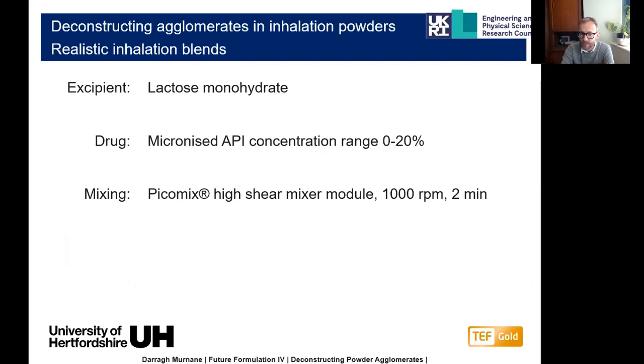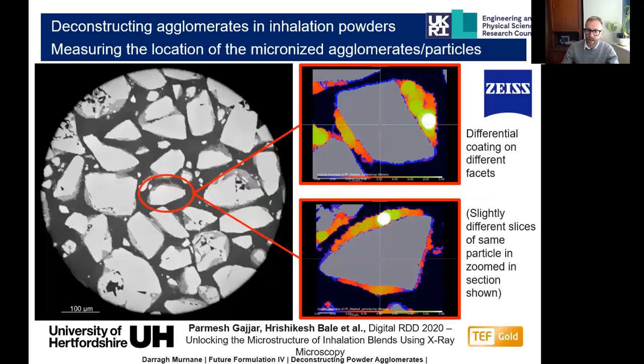We used the PicoMix, which is a small scale simulant of an industrial scale high shear mixer. Subjected it to 1,000 RPM mixing high shear for 2 minutes, which we've taken as a standard from previous literature studies using the PicoMix with good effects. And when we do that and we start to image these powders, I'm seeing there's some questions coming in here, which I will pick up as we go through towards the end of the presentation.